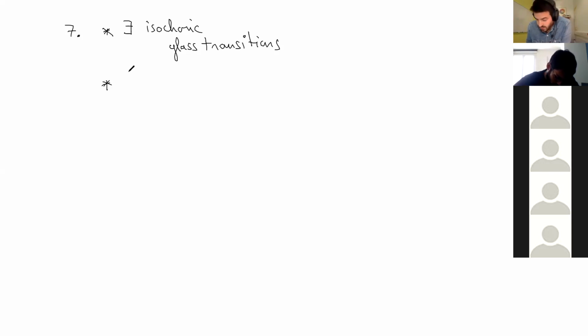Second aspect, the existence of a certain finite temperature at which the free volume equals 0 is also very criticizable, because we are not dealing with oranges or hard spheres. We are dealing with atoms, and for atoms there is no incompressible size. You could continue providing some thermal energy and continue climbing your potential, so with thermal energy you could go really to zero distance and continue to increase the travel over energy barriers. So there is no incompressible limit. You don't suddenly have an infinite barrier. You always have slopes, and kT allows you to go on those slopes.